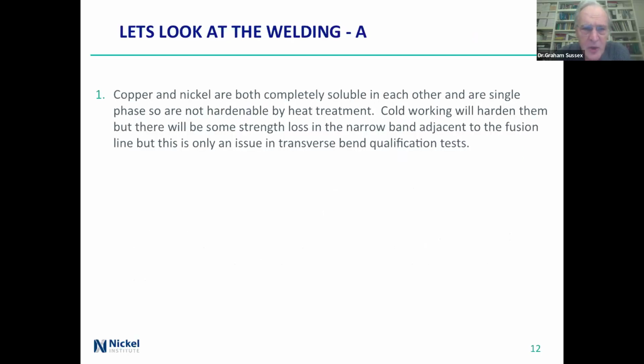So let's just look a bit at the welding. The copper and nickel are both completely soluble in each other. They're single phase, so you can't harden them by heat treatment because you can't precipitate something out and lock the microstructure up. You can cold work them quite easily, well, reasonably easily, but there will be some strength loss in the narrow band adjacent to the fusion line when you weld it up.